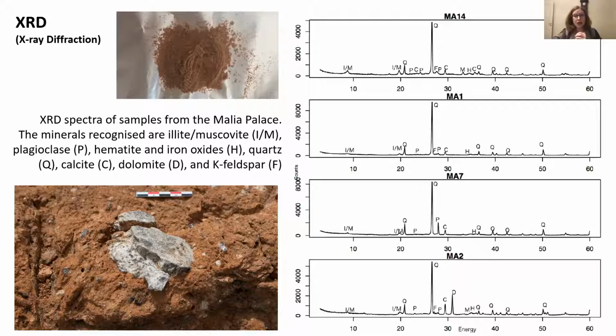Which reflects the incorporation of fragmented lime plaster in the recipe during mudbrick manufacturing. Here is an example from nearby where we took sample number 14. And thus indicating the likelihood that building materials, especially old building material, were crushed and remixed during the mudbrick manufacturing.